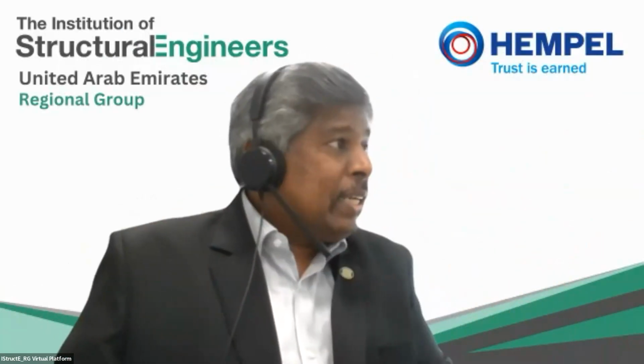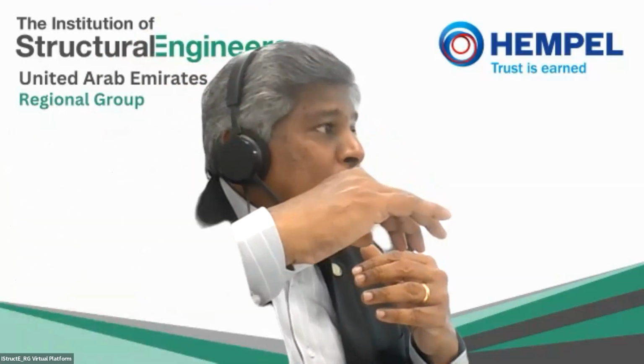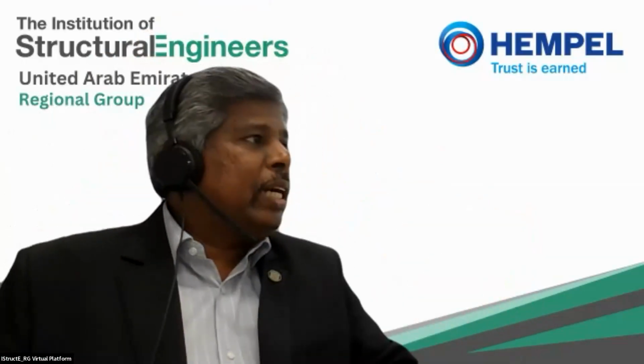So overall, when we do the testing as per ISO 12944, we subject the system to a salt spray test and a water condensation test. If you do a microscope analysis, you will find that the coating has absorbed moisture over a period of time, because even a very robust coating can tend to absorb it over a long period. So the primer is definitely there to provide duplex protection, and it ensures that the overall system is robust and you're getting the durability that you're looking for: 15 years, 25 years.